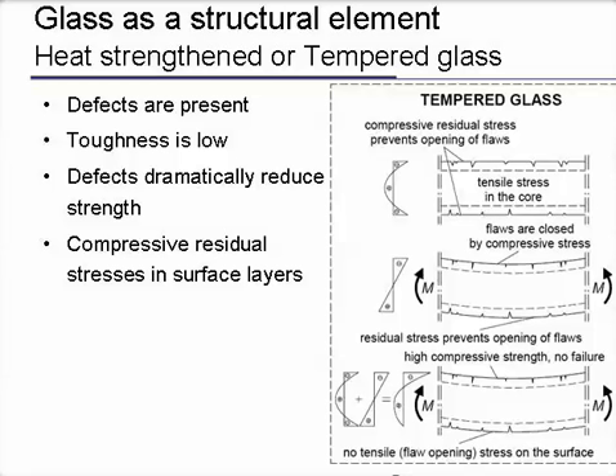When we apply this to glass, as I said, we have glass where defects are present, so we don't have a very good resistance, especially toughness is low. It can't support any defects. And therefore, you must have compressive residual stresses where you have the defects, and the defects are on the surface. So with tempered glass, that's what you do. You heat treat them so that in the end you have residual stress in compression on both the exterior and tension stresses inside where you don't have defects. The compression residual stresses go from 100 up to 180 megapascal here.